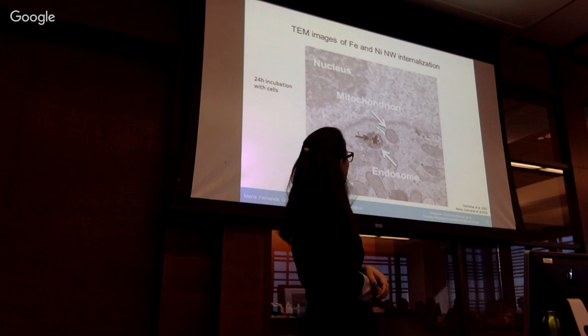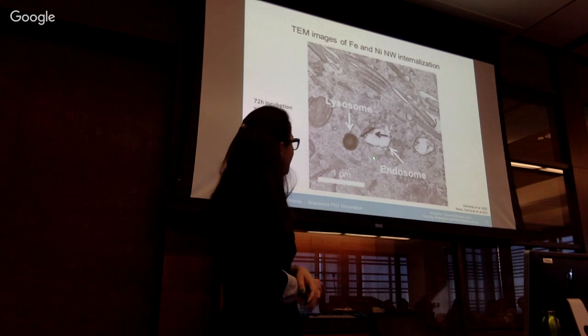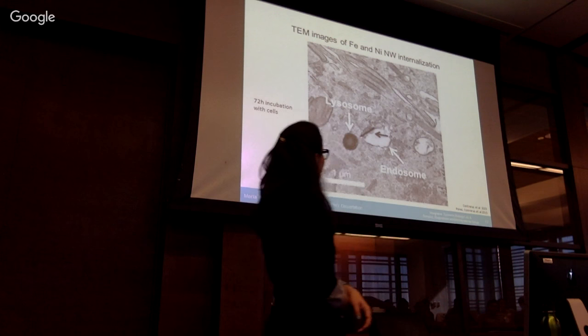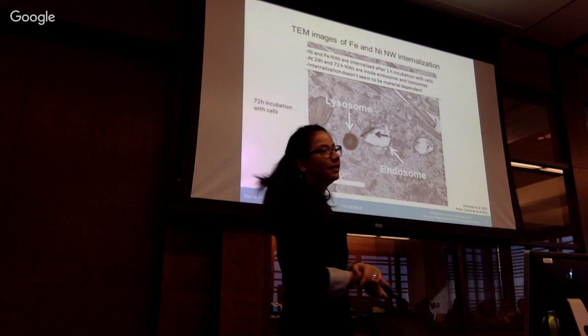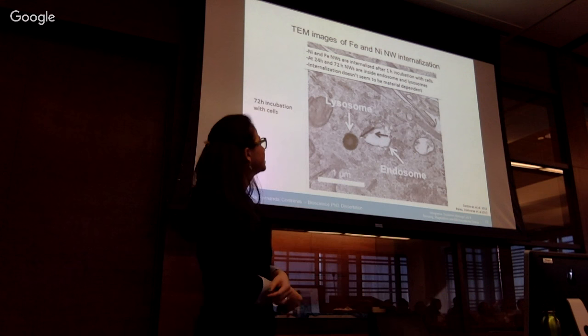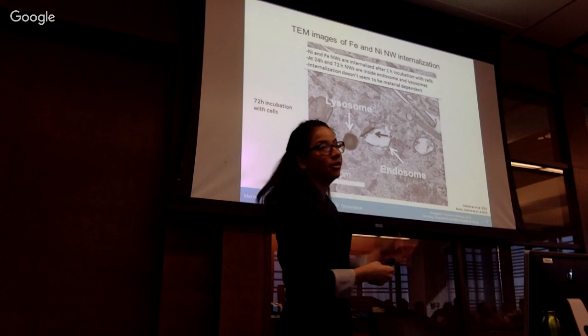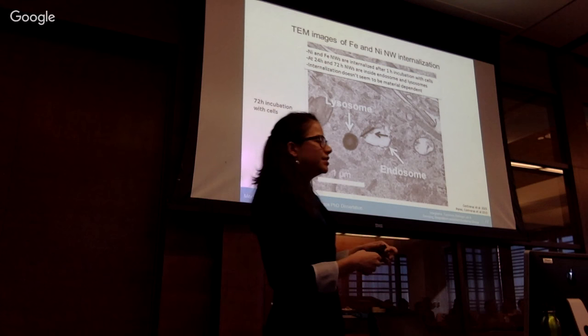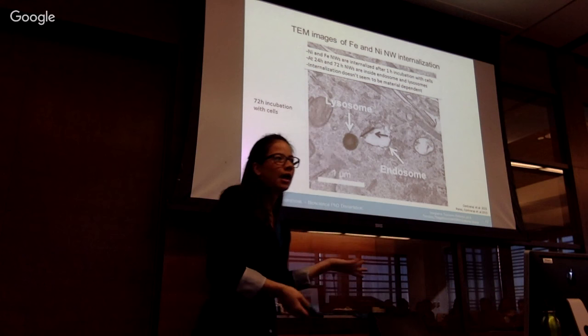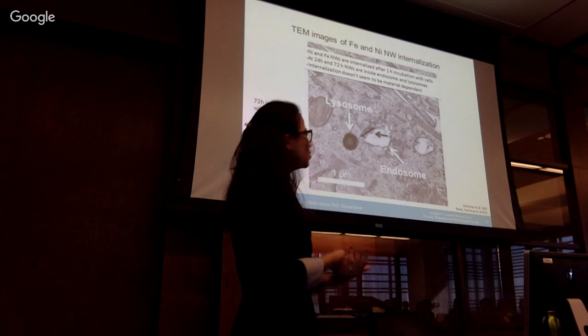If you move further, when they're incubated for 24 hours, they're mostly found inside endosomes. And if we move even further in time, we again found them in endosomes, but moving towards lysosomes. Okay, so from these images, we know that iron and nickel nanowires are internalized after only 1 hour. You can see they start to be fully internalized after 1 hour of incubation. And for further time points, they are mostly found in endosomes, but moving towards lysosomes. And this internalization process didn't seem to be dependent on the material of the wires. For both nickel and iron, roughly the same dynamic was observed. You cannot do a lot of statistics with TEM, but roughly, we observed that they are both internalized.